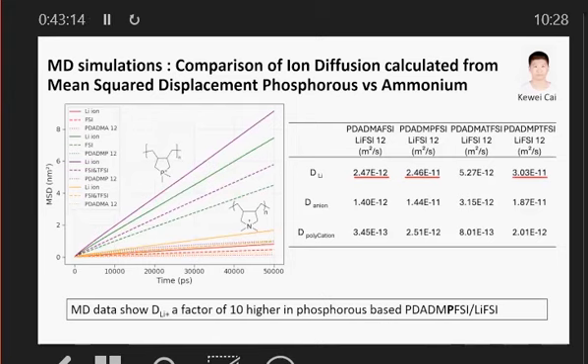So we say, okay, we can model it. Will it be a better system? So here we have the mean square displacement on the left-hand side. On the right-hand side, the extracted diffusion coefficient from the slope of these lines. We see that the blue and the green correspond to the phosphonium system. The other ones correspond to the equivalent ammonium system. We have the TFSI mixed ion and the FSI. This is all, remember, in the MD simulation.